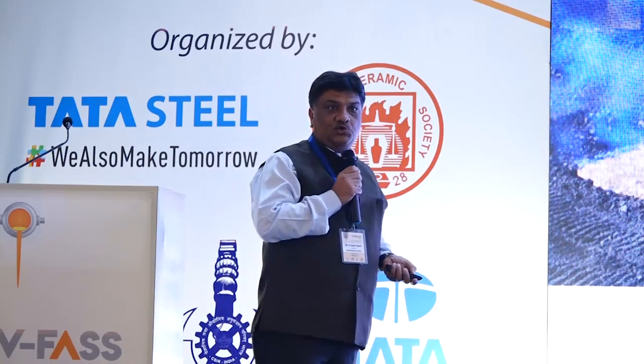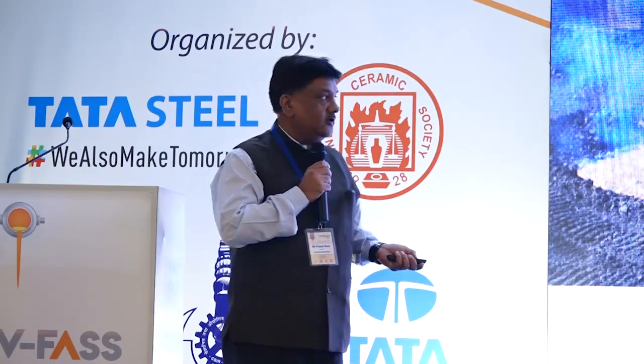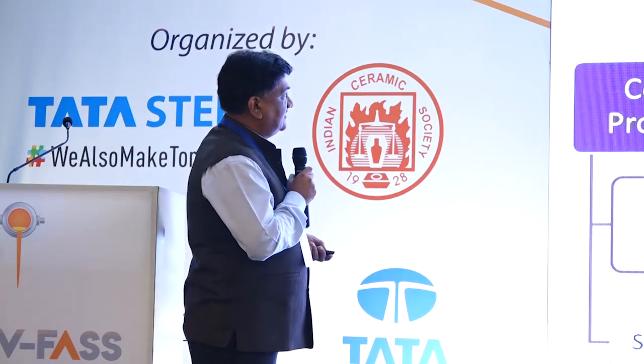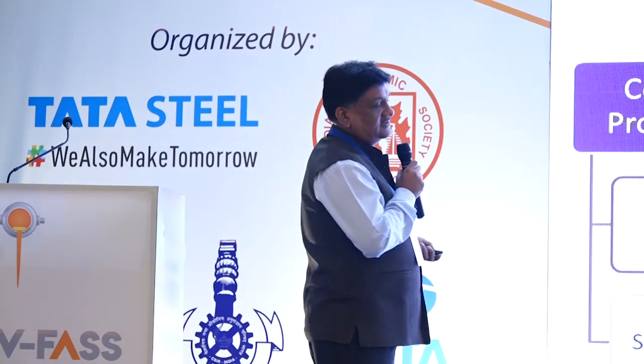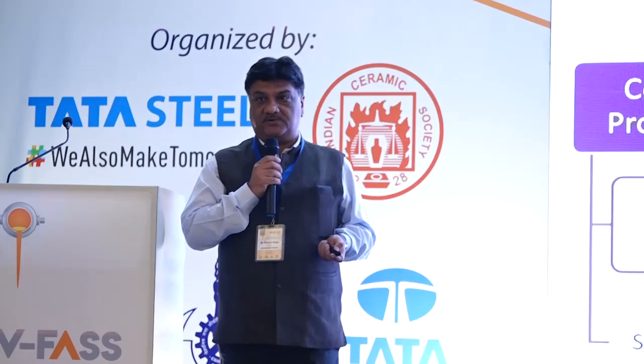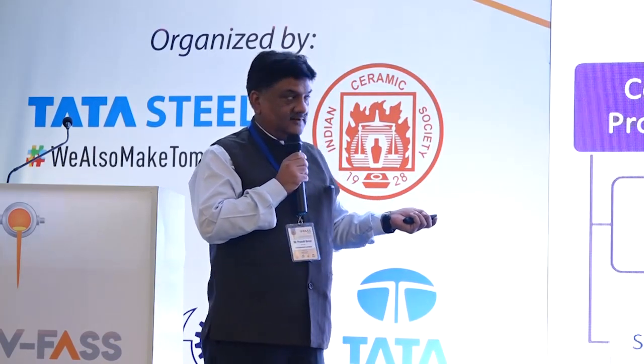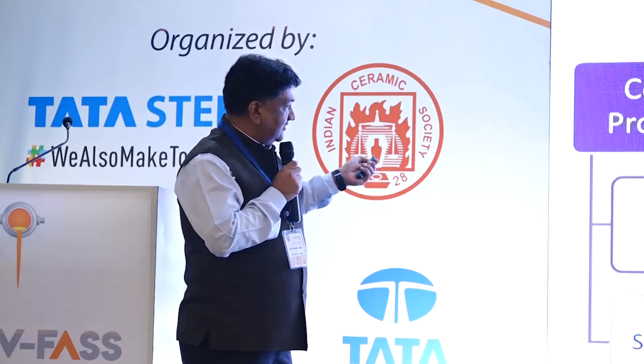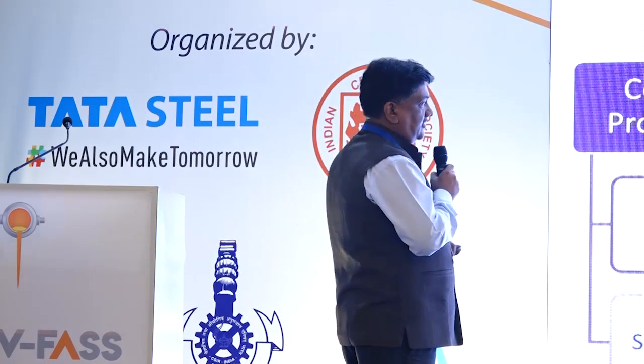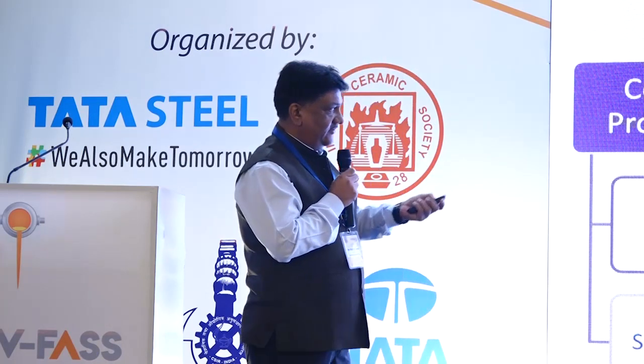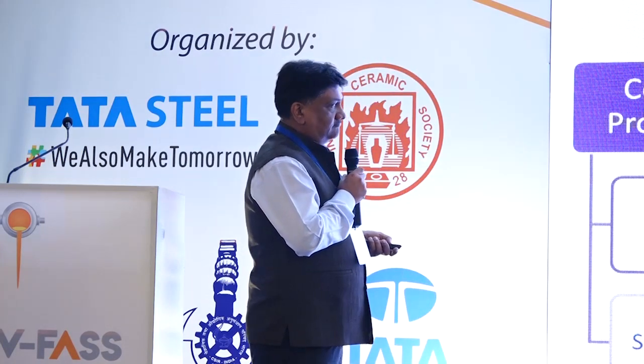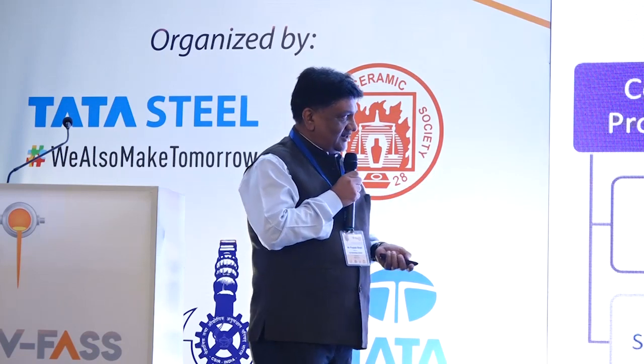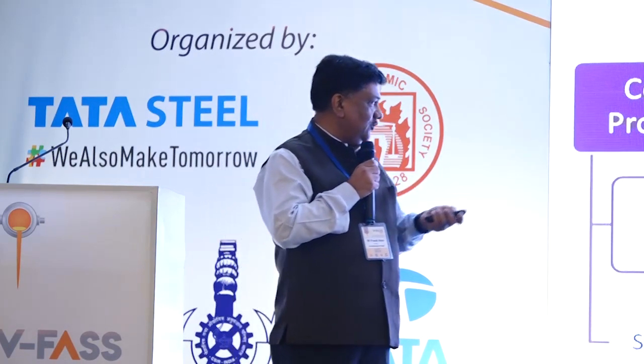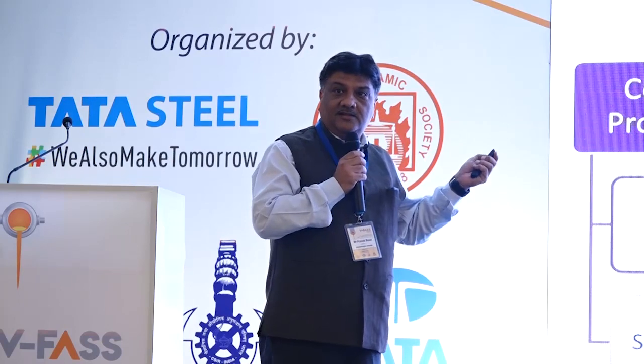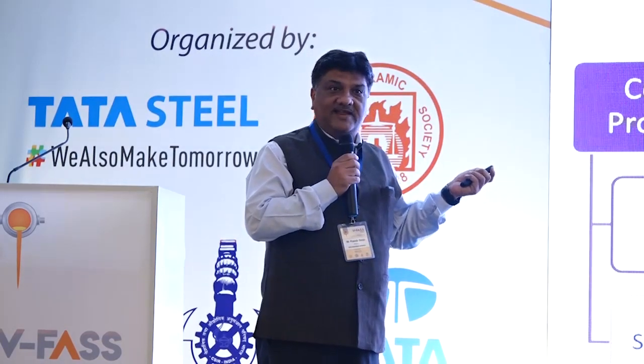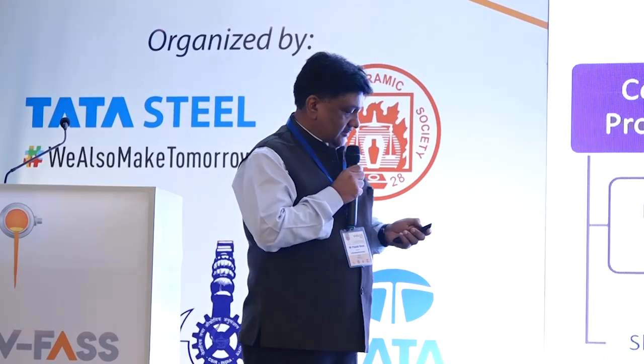LF slag, that's the new one we started. Somebody was asking about LF slag. So we did some analysis, and we attempted to replace the clinker factor by around 0.8 to 1% using this LF slag. It is good to use LF slag, replacing even up to 2%. We went with 1%. It even shows a high content of residual material of C12A7 and a low vitrification of 10 to 20%. But with the limited dosage, it is beneficial for use in slag cement.